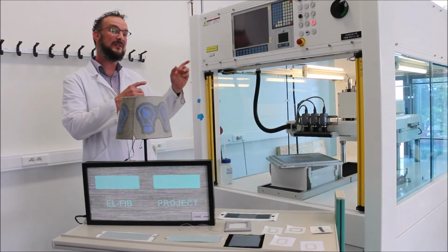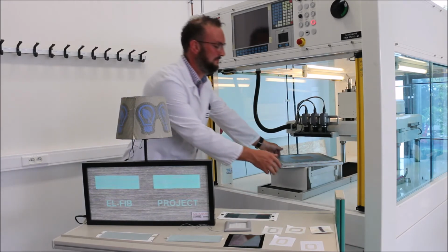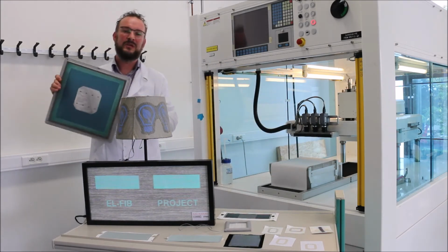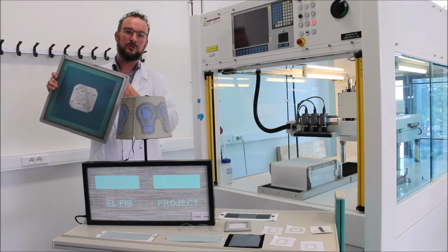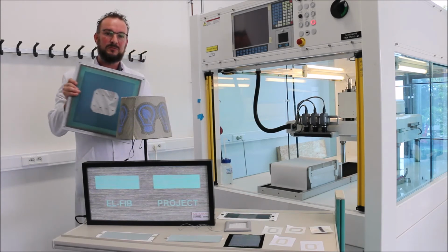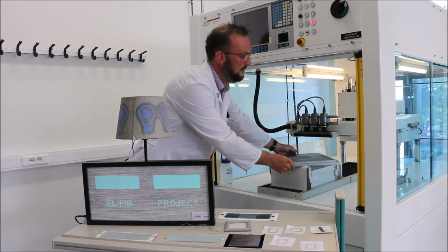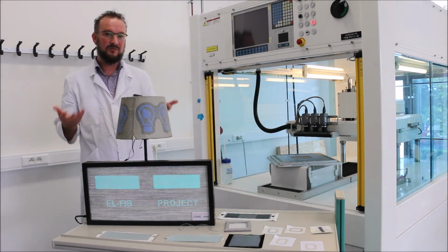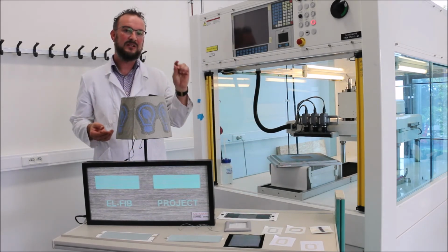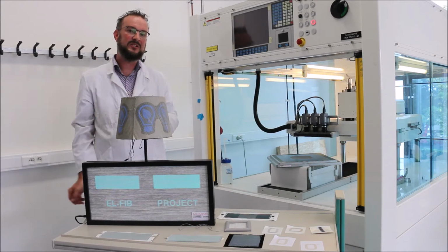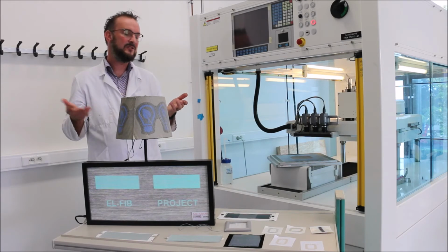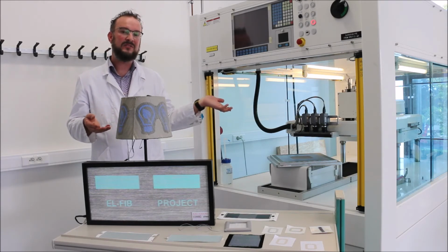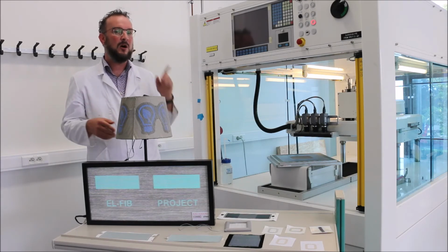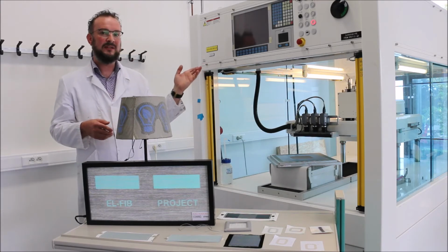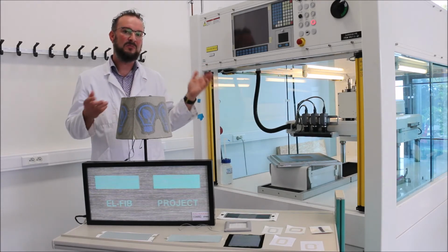The last technique we investigate is screen printing. With screen printing, we deposit viscous inks through a screen onto various substrates. And because these inks are so viscous, the final layer thickness is much thicker than, for example, with inkjet printing. With inkjet printing, we went to 200 nanometer thick layers, while with screen printing, the thickness is around a few micrometers. However, the benefit of screen printing is that the speed of deposition is much faster.